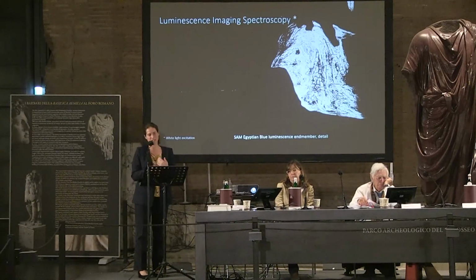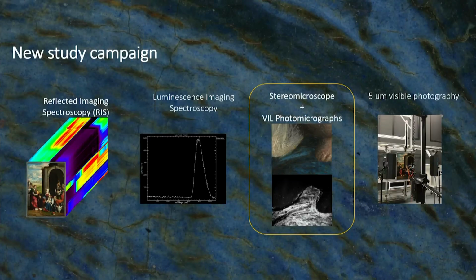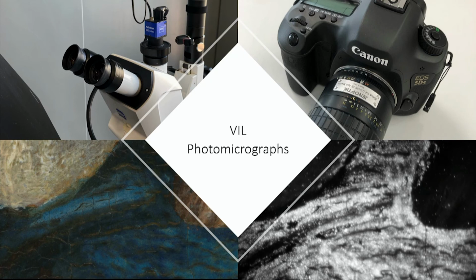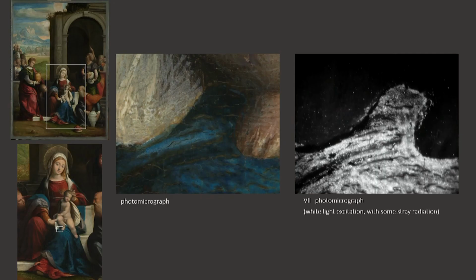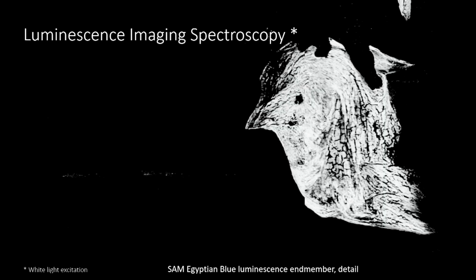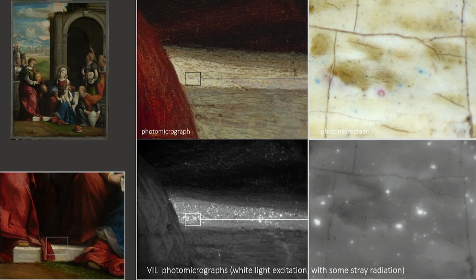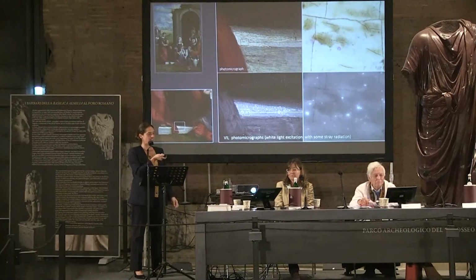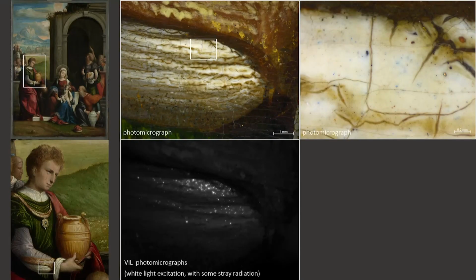I'm a painting conservator, so I went back to the object and looked at it with a stereo microscope to try and see what we're exactly mapping. We tried photomicrograph with VIL. The setup needs improvement, definitely, but we still could obtain quite interesting photomicrograph in VIL. And going back to those horizontal brushstrokes that were puzzling us, and here I conclude, they relate to highlights in the white step, and that match very well with his technique.